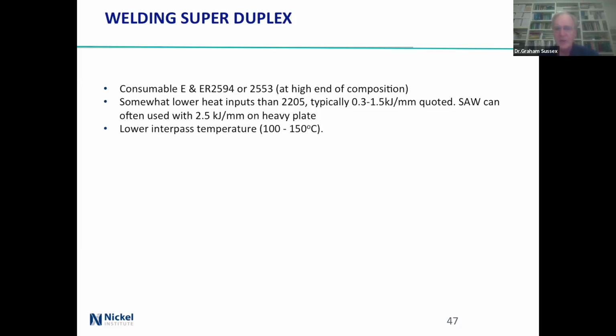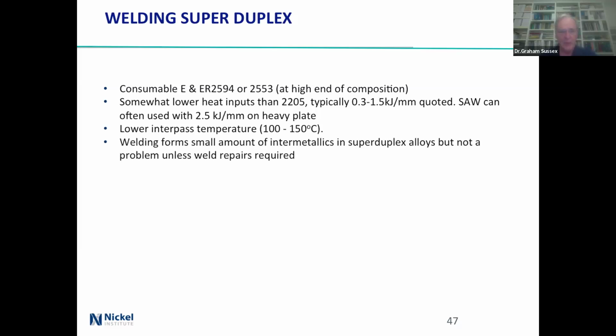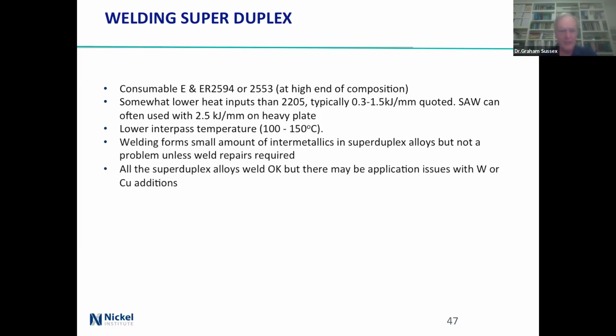Lower heat inputs than 2205. If you're talking about submerged arc, then you can often go up higher. Low interpass temperatures, because you don't want to keep it too hot for too long. And you'll get some intermetallics in the super duplexes, but it's not going to be a problem unless there was a problem already, and then you're doing another weld, and you're likely to have a similar problem, and you'll be chasing your tail.